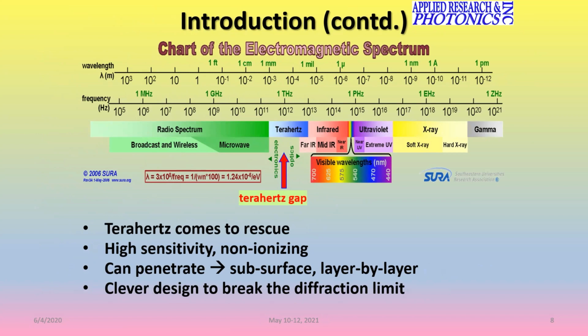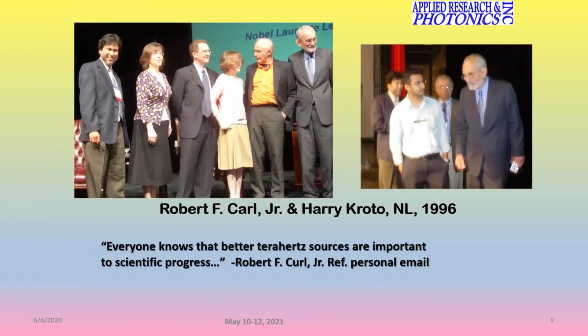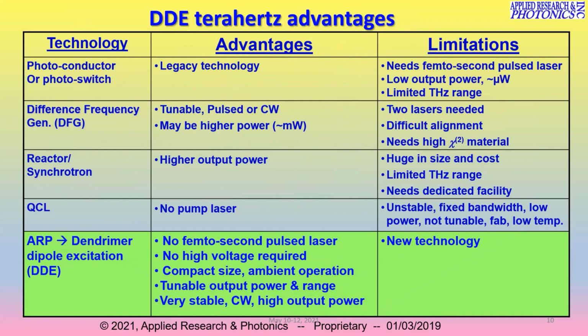as so eloquently introduced by Mehdi, Professor Anwar. T-ray or terahertz radiation used to be called the terahertz gap a few years ago, simply because there was no man-made terahertz source. Back in the mid-80s, Auston made a photo switch which could generate T-rays. He achieved about 1 terahertz or so. Power is always an issue, because most of the photo switches in vogue today generate only microwatts of power. If we use materials that absorb a little bit of power, then in transmission or even in reflection, not significant power is coming to the detector.